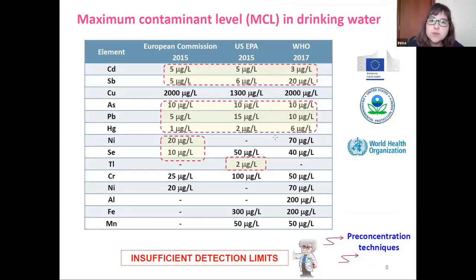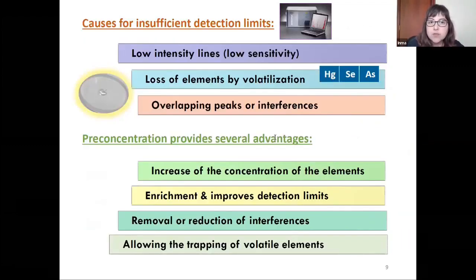If we compare these values with the maximum contaminant level allowed in drinking water according to different organisms, some of them are lower than the limits of detection achieved by TXRF, thus requiring the development of preconcentration techniques adapted or suitable specifically to TXRF in order to improve the detection limits. Some of the causes for these worse detection limits can be the selection of the low-intensity lines, the loss of elements by volatilization produced during sample drop evaporation, and the problems of overlapping peaks and interferences. Thus, in general, preconcentration strategies provide an increase of the concentration of the target analyte into the extractant phase, thus producing an analyte enrichment and improving as a consequence the limits of detection. Preconcentration also produces the reduction or removal of interferences, and it allows the trapping of volatile elements.